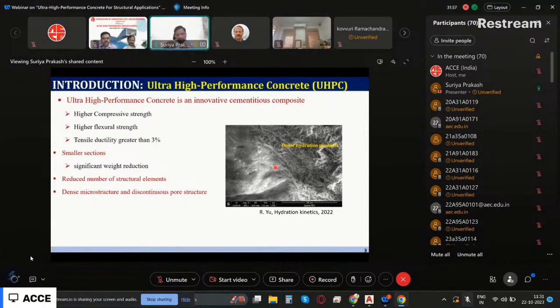Now, because I'm using very fine material in this UHPC, this fine material can go into the aggregate and form a very homogeneous surface on the interface. So you get a very dense hydration product and a dense microstructure, and even porosity is going to be less and discontinuous. Again, durability is related to the porosity and the interconnectivity of the porosity. That means if the pores are interconnected, then water, oxygen, chloride, or any other substance that is going to cause corrosion can flow from one side to another.